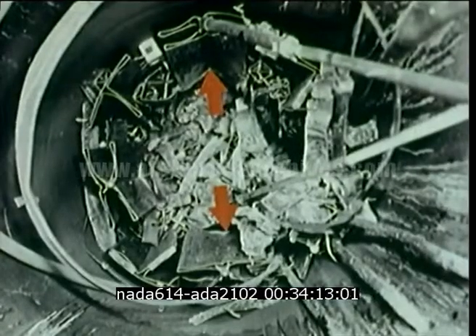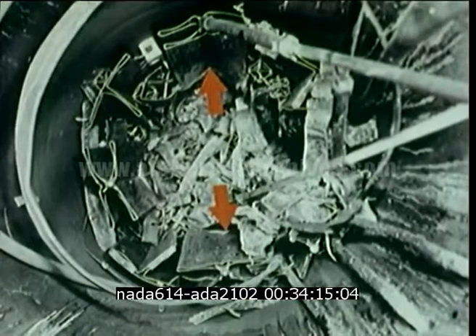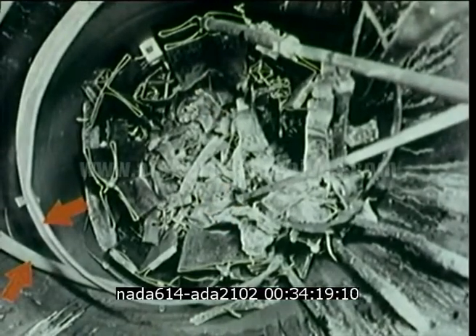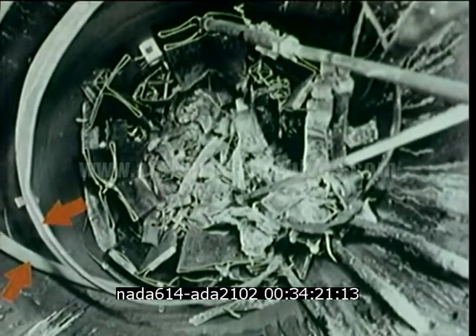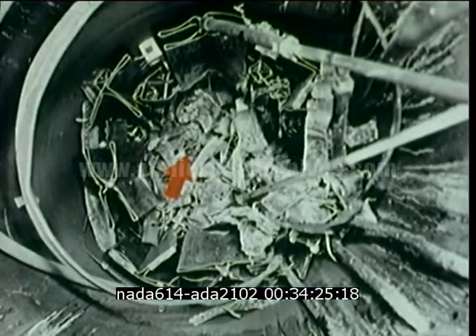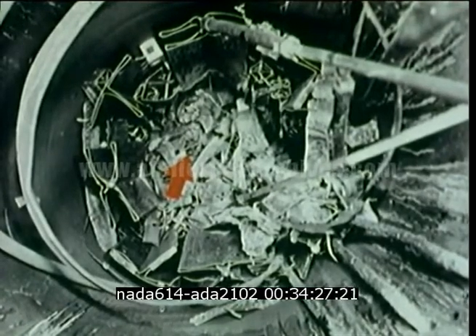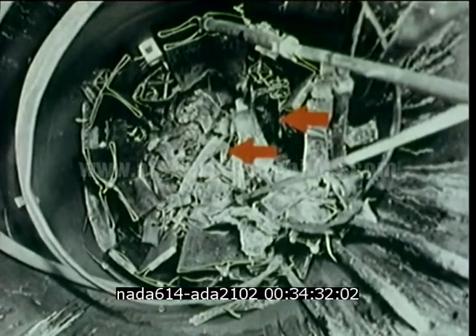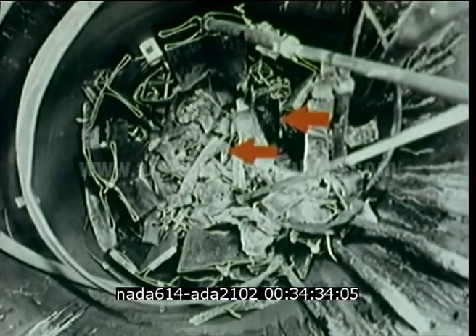Removal of the central blade and shroud laid bare the true extent of damage to the reactor. The core was radially expanded and wedged against the thermal shield. Feed water spray rings were collapsed. The 16-element central region experienced severe melting, mechanical distortion, and complete disarrangement. A number of flux wires inserted just prior to the accident were also visible.